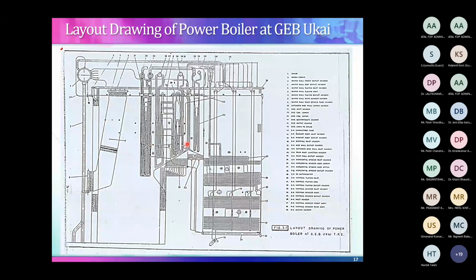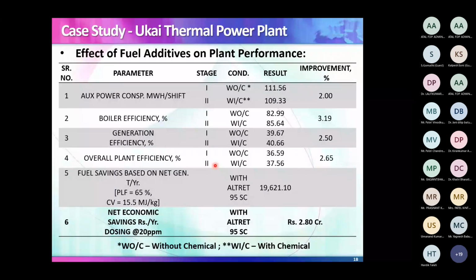And this is the effect which we got. Auxiliary power consumption without the use of additive was 111.56 megawatt hours per shift, and with it, it has reduced. That means your fouling has definitely reduced. Boiler efficiency has increased from 83 to 85.64. Generation efficiency has improved from 39 to about 40.661%. And overall plant efficiency is improved from 36.59 to 37.56%.